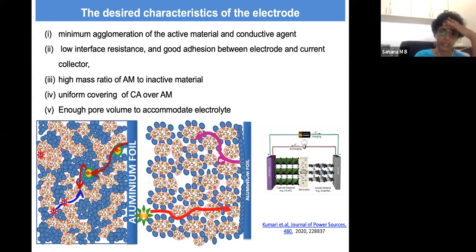In addition to that, if you have a higher amount of carbon black, then it is increasing the inactive component in the material, so gravimetric energy density comes down. Similarly, with a higher percentage of pores, gravimetric energy density comes down. So we need an optimum percentage of carbon black, which is uniformly distributed, and a very good distribution of pores for the electrolyte to go through.